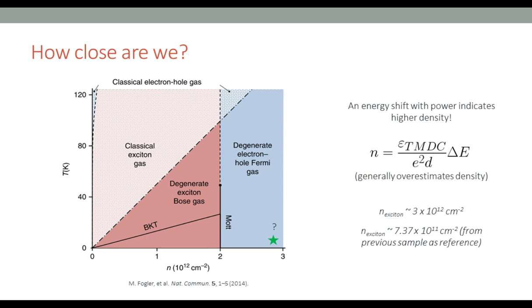and also this extraction of the density is only valid in the linear regime, but with the strong interactions that we saw in the diffusion, it's possible that this regime is not valid. This equation is not valid for this regime, but it gives us a rough estimate, and it also shows us that we're able to increase the density from where we were without any trapping. So this is the future direction of what we're looking for, to explore this phase space by changing the density and or the temperature of our excitons.